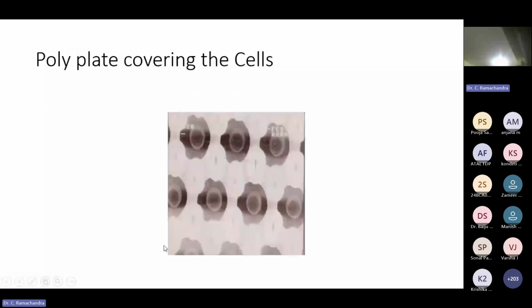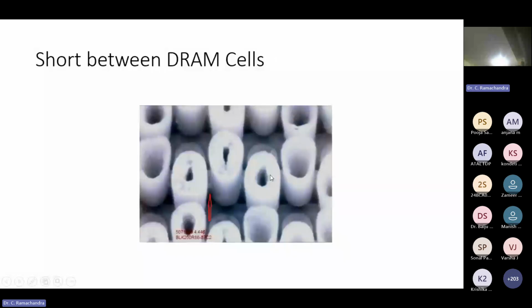So this is what you see, polyplate covering this cell. There is this whole polysilicon plate, very thick. You have to remove it in a controlled manner. So then we did so many experiments. These are all the memory cells. When I say memory cell, for example, data 1 is stored in a DRAM memory cell. This is the cylindrical structure. This is the way data 1 or 0 is stored. There are 512 million memory cells. So I can see every individual cell, and now you can see there is a short between these two cells. So we were able to see a short between two cells in a very effective manner. This is the technology I developed, of course, 20 years back, but it was quite challenging and good.